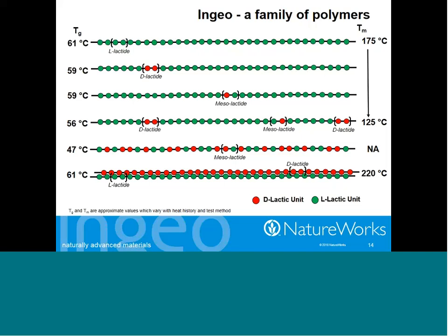The other thing I'll mention is that you can see the glass transition temperature is depressed slightly as we add bits of D-lactide and mesolactide, and the all-mesolactide polymer is significantly depressed from the 60-degree glass transition temperature that people think of for PLA.